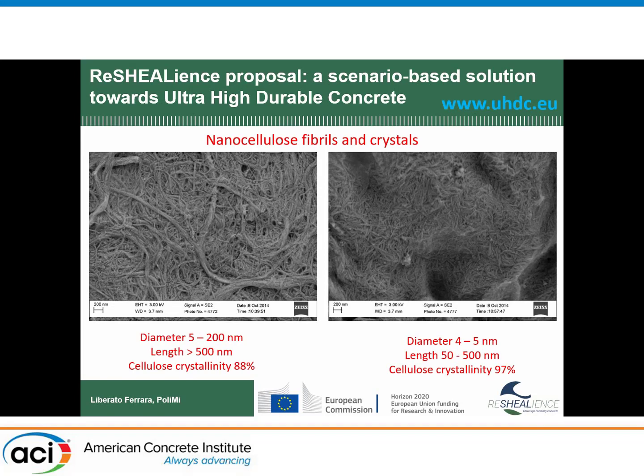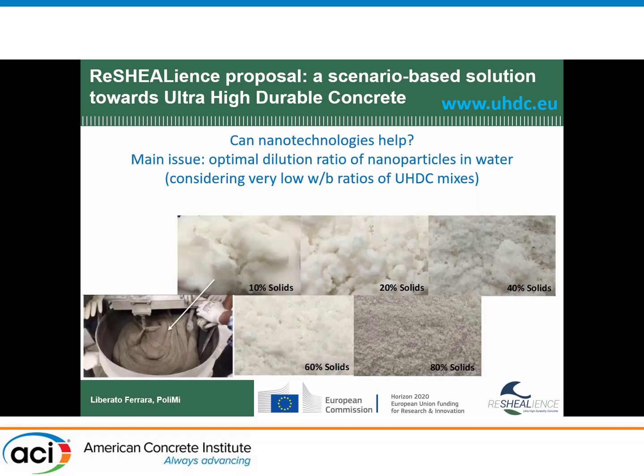But in UHPC, we have about 200 liters of water per cubic meter, and we wanted to dose the nanocellulose. Even if you use 0.1, 0.2% by cement weight, all the water that is in the nanocellulose dispersion is probably higher than what you need to mix. So there was an issue in the beginning to be solved. They had to provide the nano pulp dispersion at a much higher concentration. So we ended up with something which was 10% of solid, and we had to make a two-stage mixing because in the beginning we have to further disperse it with sonication and then add into the mix.